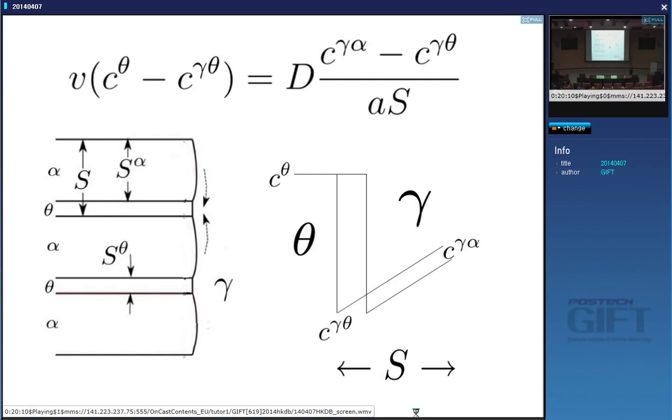And you can see clearly that S, the diffusion distance, is constant. So there is nothing to solve here. The velocity is equal to this term divided by this term. Very simple growth rate calculation. You can say it's half, because that is the diffusion distance. Because stuff over here moves here and stuff over here moves here. But it could be less than half because this is the extreme distance from here. This takes a shorter distance here. But don't worry about that.